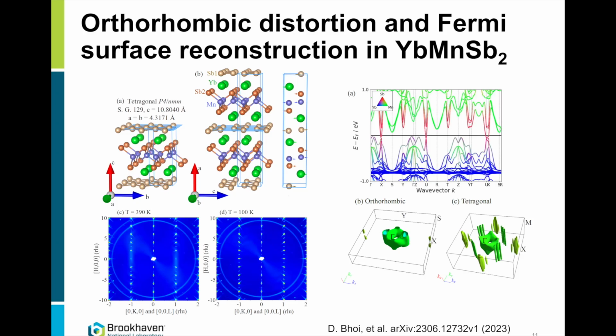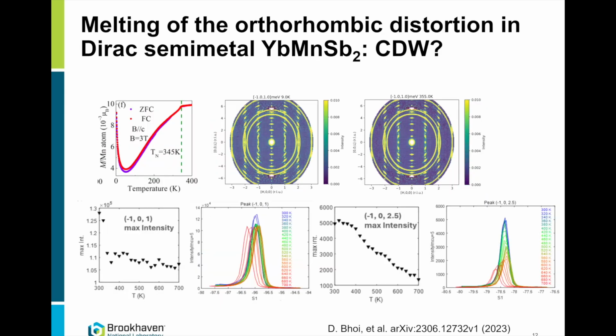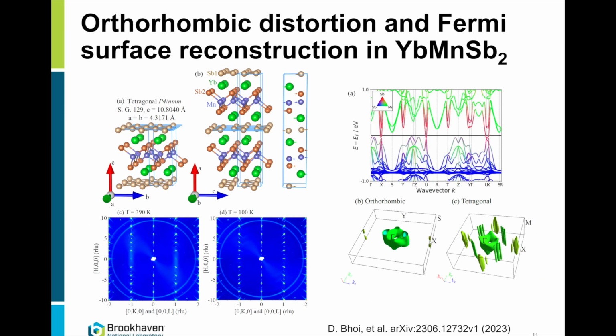Now what we see here is what we have shown, that calcium manganese dibismuthide actually undergoes a distortion at around 50 Kelvin. Another material that was also recently reported to have the same distortion is ytterbium manganese diantimonide, and it's Uwatoko group measurements. So they showed the neutron diffraction evidence for the distortion. It's again a very similar formation of zigzag chains here in the antimony layer, this time not in the bismuth layer. And there is a Fermi surface reconstruction where one Dirac cone remains, but the other one in the perpendicular direction goes away. So it is a Peierls distortion.